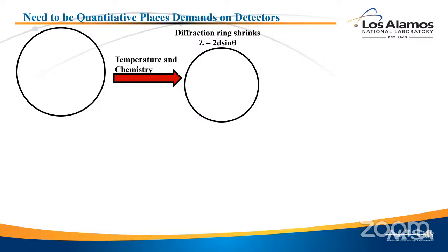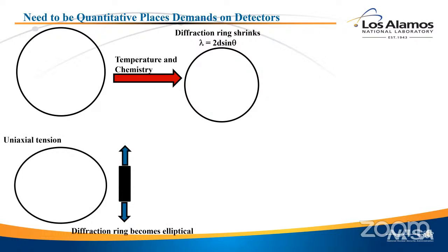Now, this can get a little bit more complicated if you think of second order interactions, but in terms of first order, if you change the chemistry, if you change the amount of vanadium in solution in Ti-6,4, you just change the radius of that Debye-Scherrer cone. So it's hard to segregate chemistry from temperature if you don't know anything else a priori. You usually have to know something else, like measure the temperature a different way.